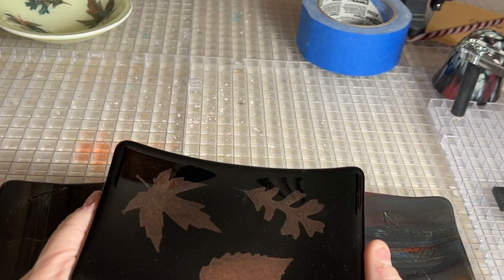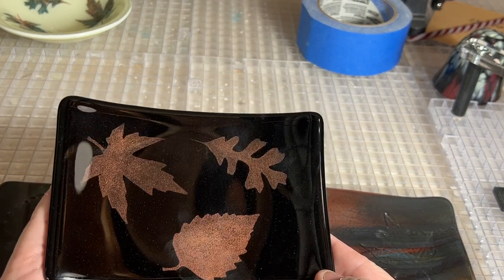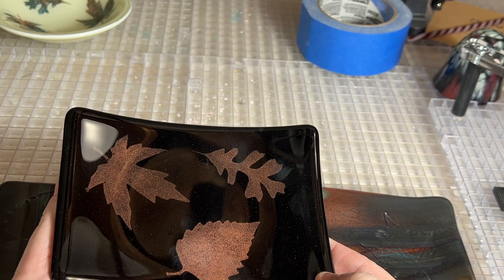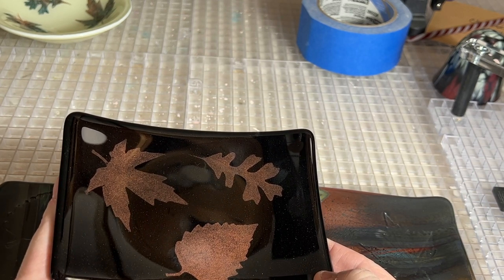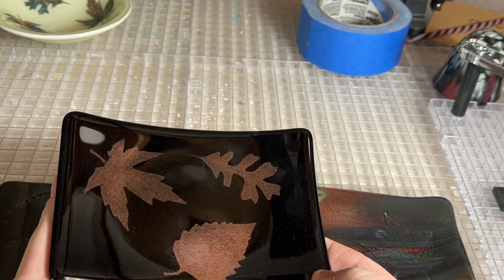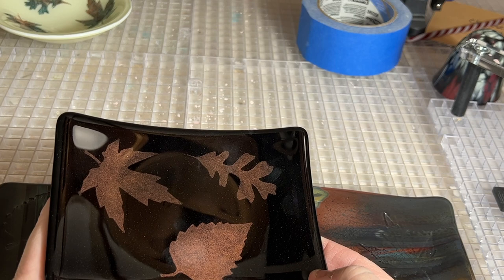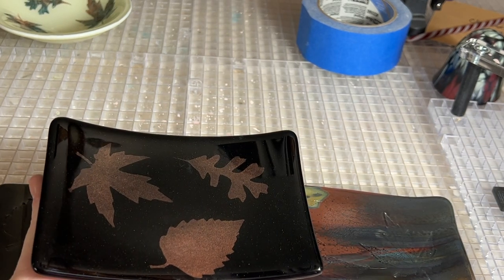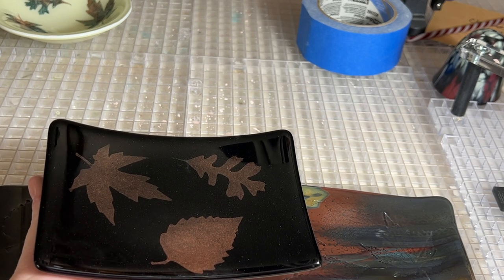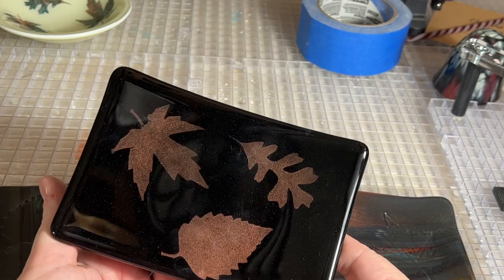This was the mica paint that I screwed up and did a hotter full fuse schedule. I should have only gone, actually I did go back to my notes since I recorded last, and my mica paint video that's also out there on YouTube, and I'll have it linked in the description below, I only went to 1385 and I still got a nice fuse. So know your kilns. If the lowest temp that you can get a nice full fuse at is where you would want to go with doing the mica paints.